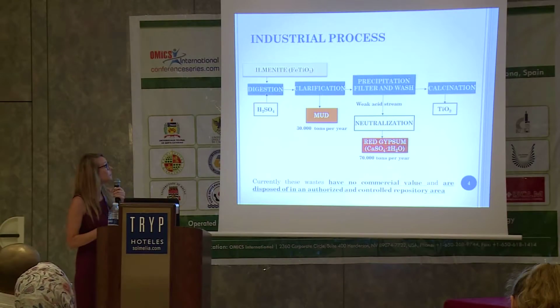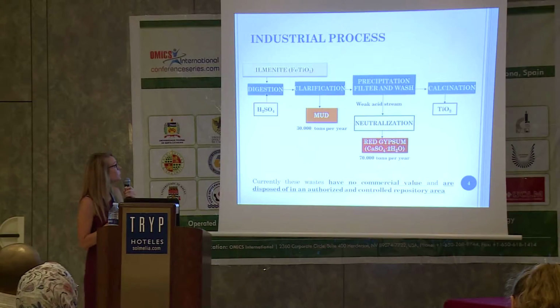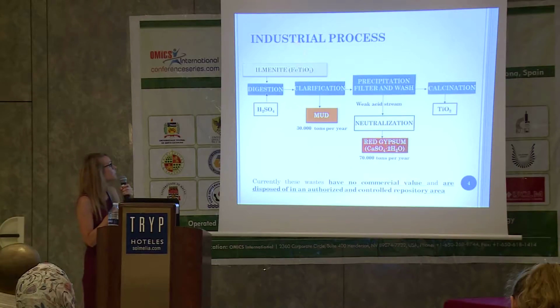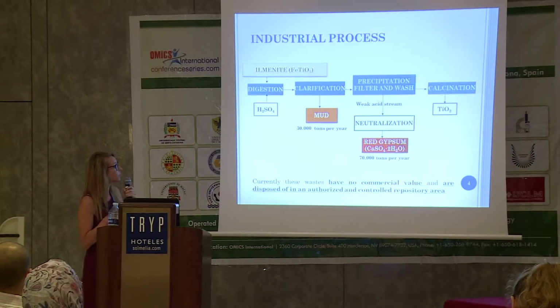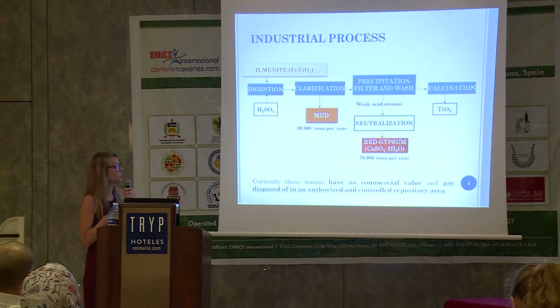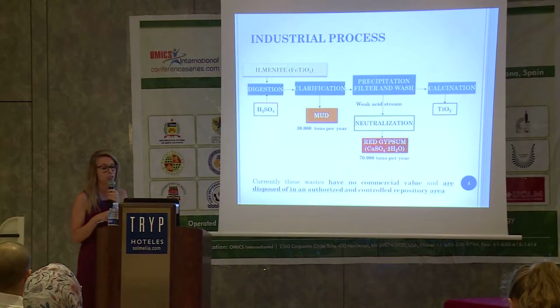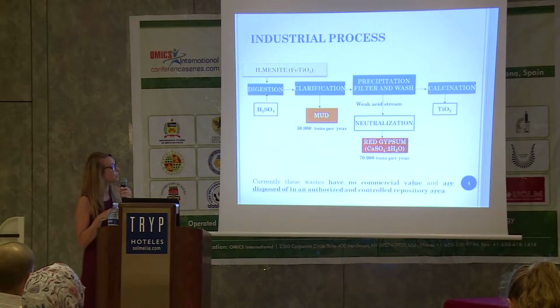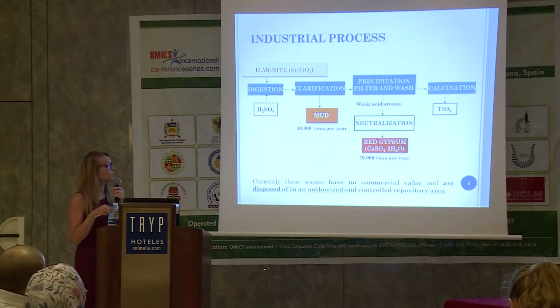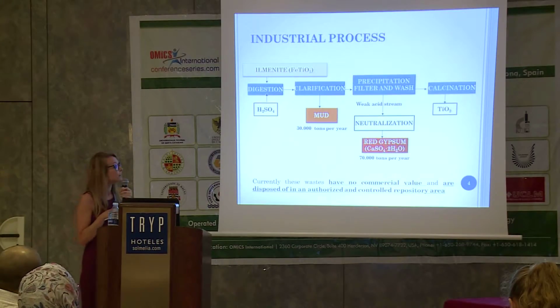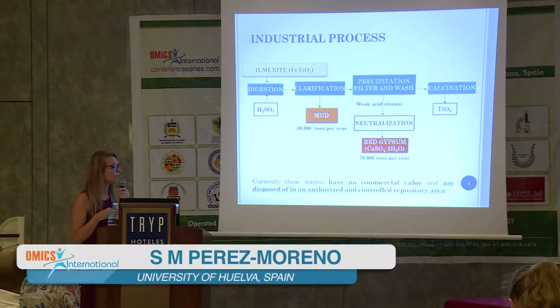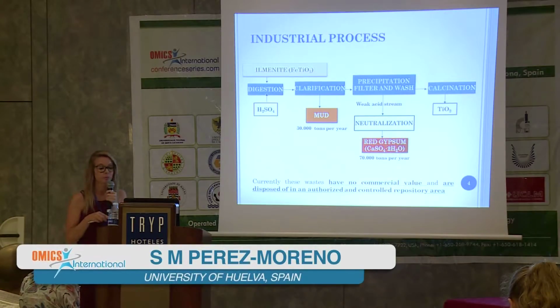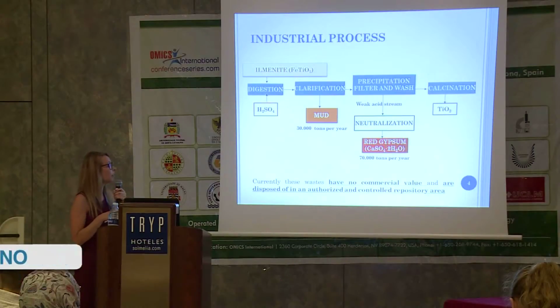In this slide, I present the industrial process. You can see that the raw material is the ilmenite that is digested with sulfuric acid. After a clarification step, the mud is generated. It is the first residue that this industry has. The titanium dioxide is produced after a precipitation, filtering and washing, and calcination step. During the washing step, a weak acid stream is generated, and after neutralization with calcium hydroxide, the red gypsum is generated. Large amounts of these wastes are produced,